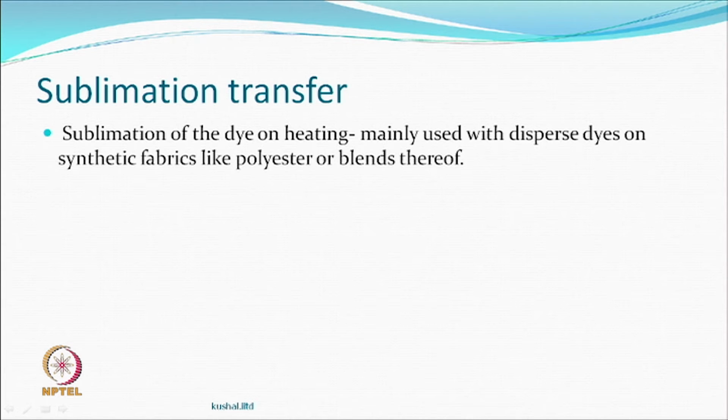When somebody designed disperse dye, they were not hoping this would happen, although during fixation you had thermosol fixation also, and they understood this could be the mechanism also. So, as long as you are interested in using a disperse dye and a synthetic fabric like polyester, because even today, with all synthetic fabrics, acrylics people do not dye. You can dye acrylics with disperse dye, we do not dye. You can dye nylon also with disperse dye, but you do not dye, right. So, it is the polyester which you dye with disperse dye. Actually, disperse dye and polyester is the best combination as far as transfer printing is concerned, which is sublimation transfer printing.